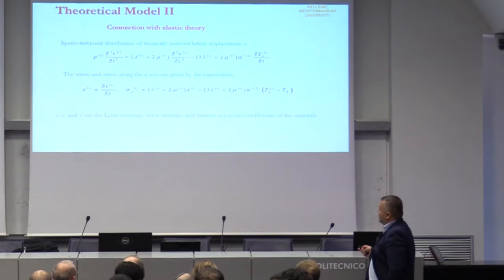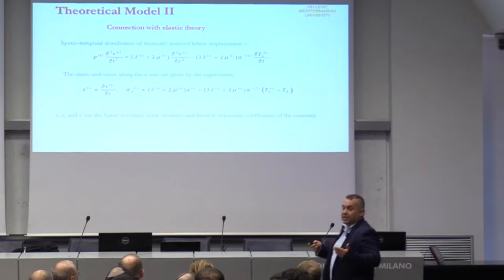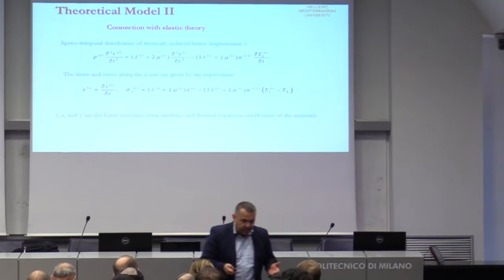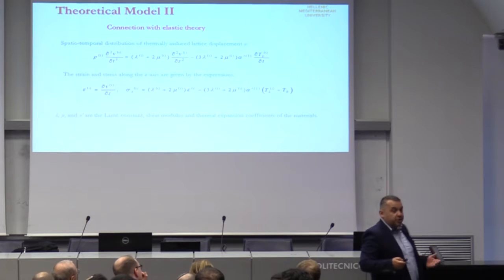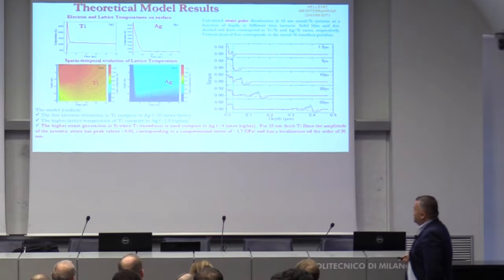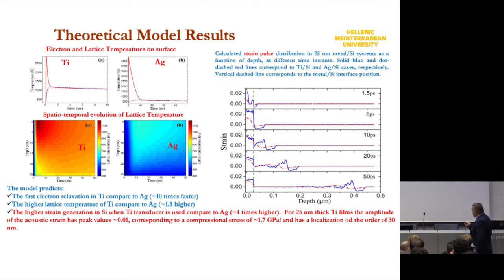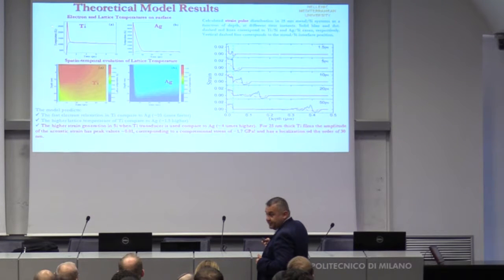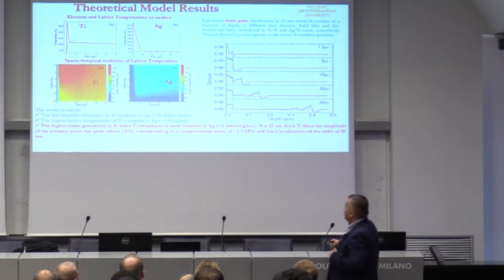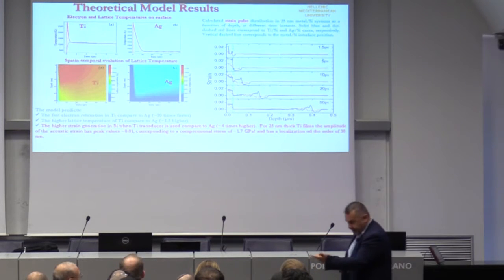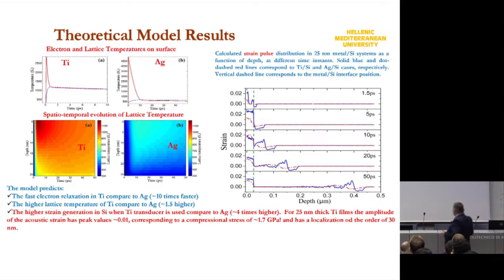We can solve these equations in order to calculate, for example, the lattice temperature and the strains and everything. If we know the lattice temperature, we have a spatiotemporal distribution of thermally induced lattice displacement, from this equation, where we can then calculate the strain and the stress. We can see, in a certain material, under certain illumination and laser characteristics, whether we have an explanation of the effects that we have measured experimentally.